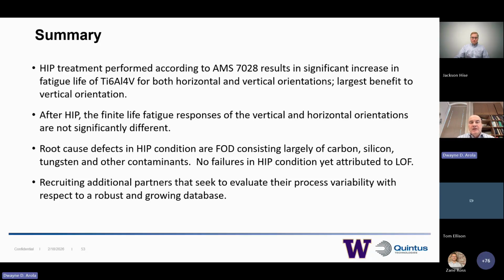After the HIP treatment, the finite life fatigue responses of the vertical and horizontal orientations became not significantly different, which was fantastic. The root cause defects in the HIP condition are what we found is FOD consisting of carbon source, silicon, tungsten, and then some other small traces of contaminants that we don't have necessarily time to talk about here. But none of the failures in the HIP condition actually were attributed to lack of fusion voids.